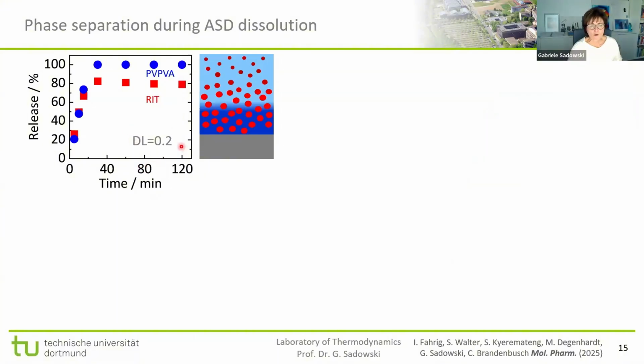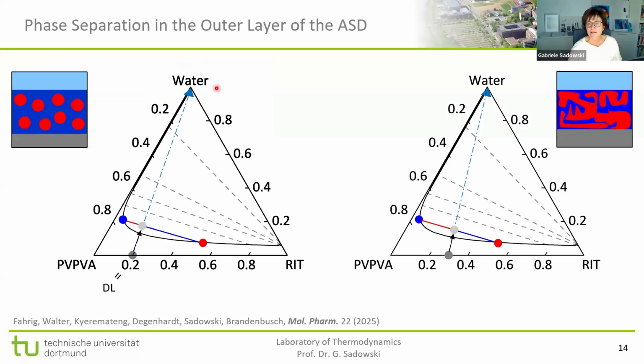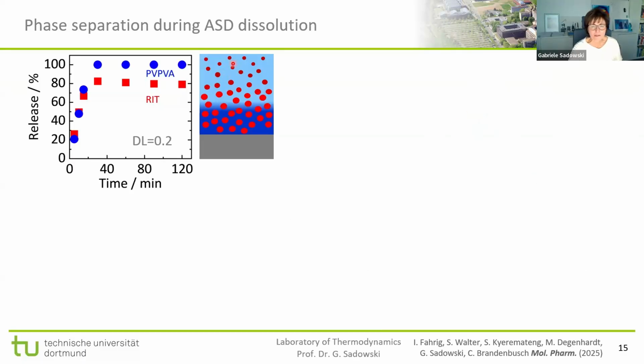This is the 0.2 case where we have a dry tablet, and this is a gel phase, which already absorbed water, where we have the phase separation in the system, but we do have a release of the droplets. But according to the previous picture, if we are up here, so in the dissolution media, we have, of course, a huge amount of water, and we are still, as you see, in the miscibility gap. So that means that the immiscibility doesn't stop here.